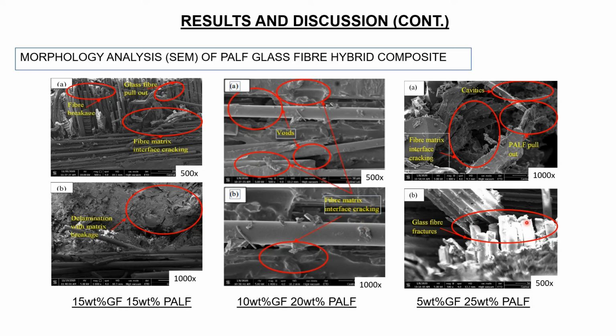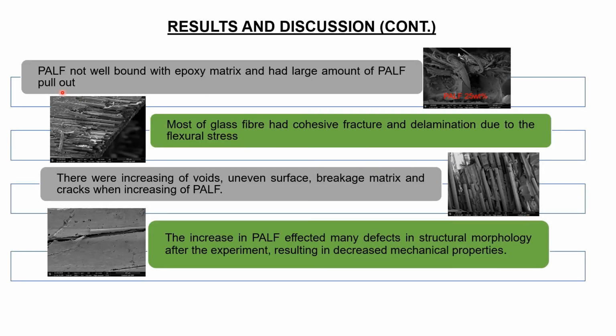But for the last one, 25%, you can see that there was a lot of cavity, PALF pull out, fiber matrix interface cracking, and glass fiber fracture. So we can say that PALF is not well bound with the epoxy matrix and had a large amount of PALF pull out at 25% of PALF. Most of the glass fiber had cohesive fracture and delamination due to the flexural stress. There was an increase of voids, uneven surface, matrix breakage, and cracks with increasing PALF. The increase in PALF caused many defects in structural morphology after the experiment, resulting in decreased mechanical properties.